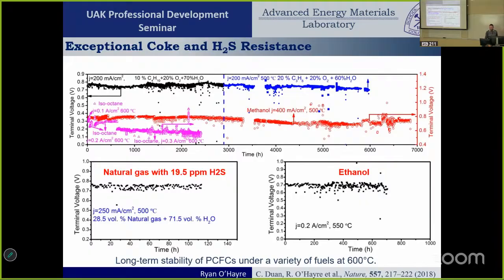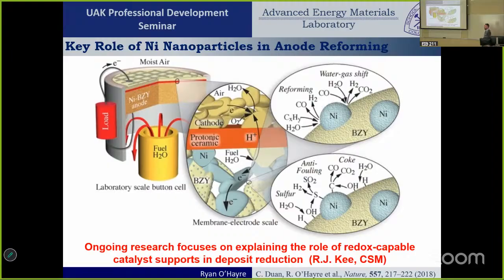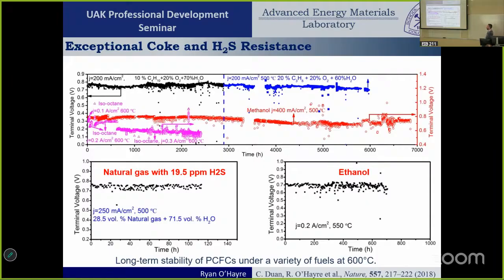Does it matter if your load is not constant current or a constant load? So there are many things you can explore about that. This was the simplest kind of test where we just did a constant load. But yes, you can look at different steps. Interestingly enough, we talked about the reversible cells where you go to electrolysis mode. That is actually protective to lifetime. So if you switch the fuel cell's polarity and run it in reverse, it'll kind of eat away some of these species, oxidize them, get rid of them, and clean the fuel cell. So by switching back and forth and running it backwards sometimes, you can actually extend the life of your device, which is really fascinating.